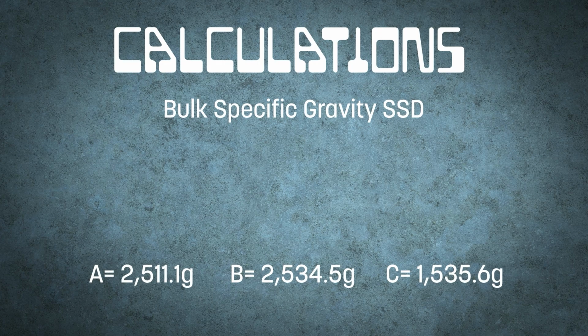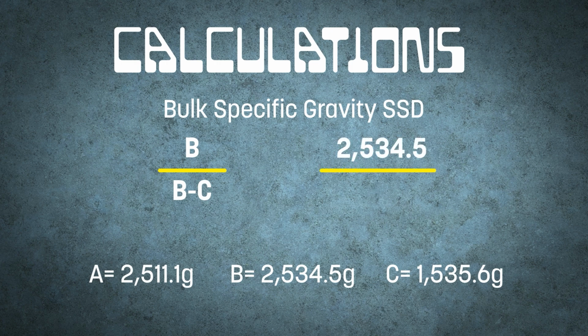The calculation for bulk specific gravity in the SSD condition is B divided by B minus C, or 2,534.5 grams divided by 2,534.5 grams minus 1,535.6 grams. And this should come out to be 2,534.5 grams divided by 998.9 grams, giving us a bulk specific gravity SSD of 2.537.